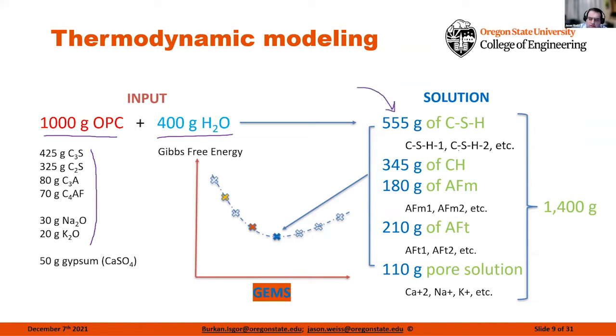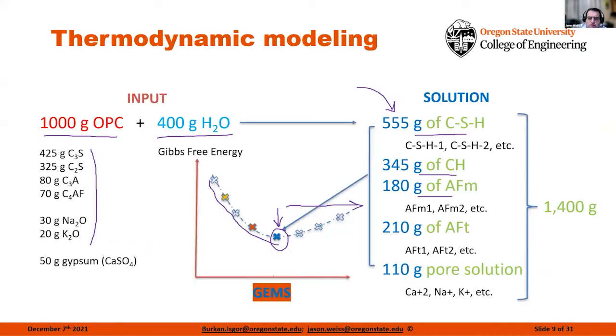What would the energy state be if we predicted this much CSH, this much calcium hydroxide, this much ettringite, right? And we do this over and over again to get to the point where we get to the lowest energy state. And it's actually this lowest energy state that is exactly the composition that we're predicting that we should have for these systems.